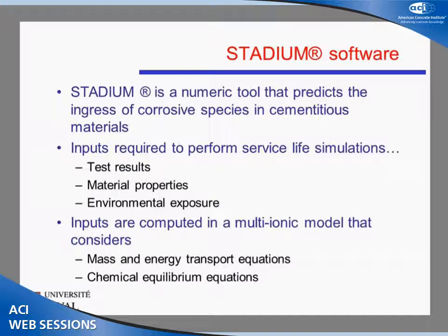Now, Stadium is a numeric tool that predicts the ingress of corrosive species in cementitious materials. Inputs that are required for this software are the test results that I presented on the last slide, the material properties, that is water binder ratio, chemical composition of binder, and so on. And very important, the environmental exposure, because it's not necessarily going to be the same if it's a dry dock or a pier or the beam of a bridge. And with these inputs, the model is a multi-ionic model that considers both mass and energy transport equations and chemical equilibrium equations that are necessary to understand how the contaminant ingresses.